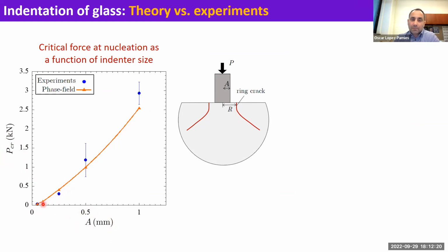And before, I knew nothing about glass and I knew nothing about indentation. So this was very interesting to me, that now I finally understood why in trains you have a hammer and the hammer has a very pointed tip. It's because if the area of contact of the hammer with the glass is small, the force that you need to apply to nucleate fracture is small.